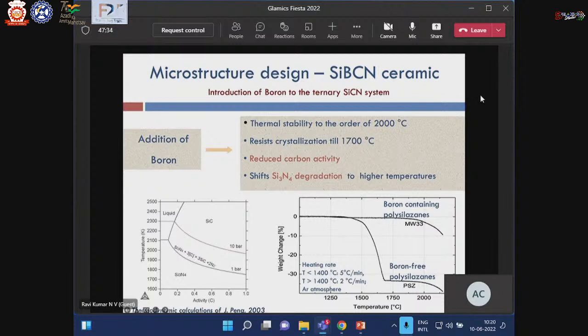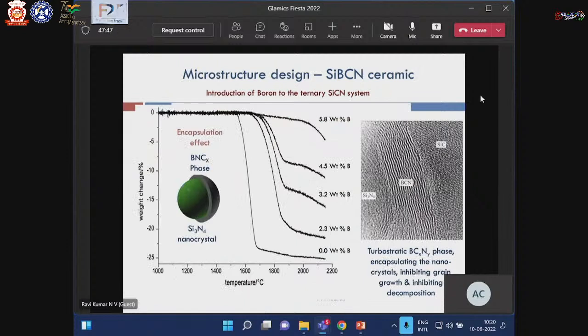Because we know, and I already demonstrated in the previous slides, that silicon nitride is the phase that is going to degrade. The strategy was basically to make sure that silicon nitride doesn't degrade. And the whole concept of making sure that silicon nitride doesn't degrade is to add boron and form this thermostable boron carbon nitrogen phase, which you see in the high resolution transmission electron micrograph here, which basically protects silicon nitride and makes sure that it doesn't decompose. Therefore, such a material system is stable till 2000 degrees Celsius. And as you see from the thermogravimetric analysis here, it is quite stable beyond 2000 degrees Celsius.